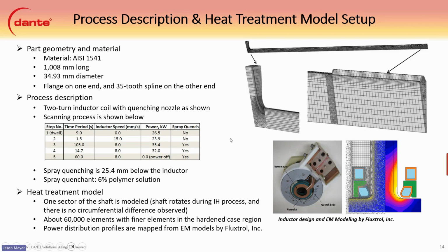So for the heat treatment model, we modeled one sector of the shaft, basically one of the splines, and cut it down the entire length using symmetry on the axle. We could also use symmetry in two ways here because the axle is spinning, and so there's really no circumferential difference in heating around the part. So we were able to basically use this model here to accurately represent the induction heating. We packed about 60,000 elements into this model, with more elements in the case region to capture the really high gradients and the stress concentrations in the part. And then we used power distribution profiles that were mapped using that Joule heating that we were talking about from Fluxtrol. They did some great work here on the EM modeling, and they gave us the temperature history that we can use for the flux.